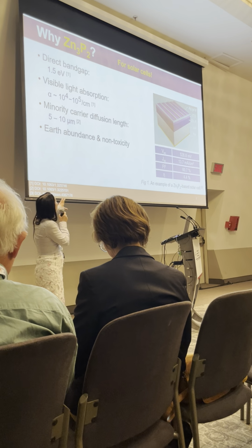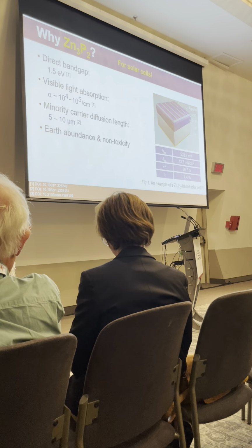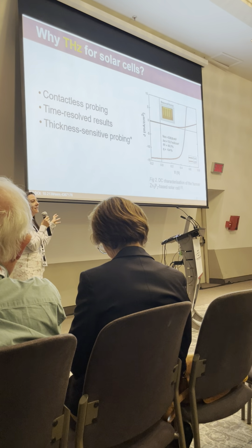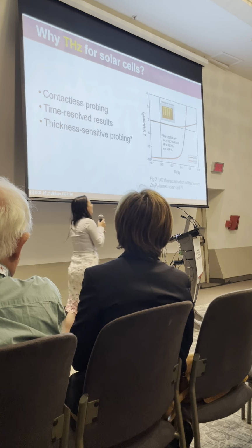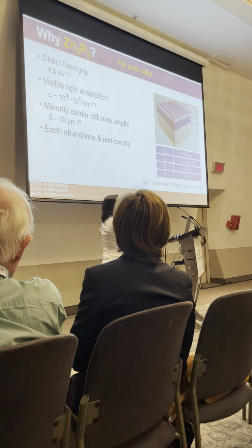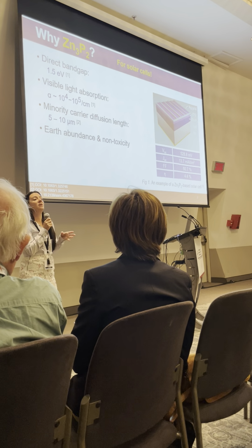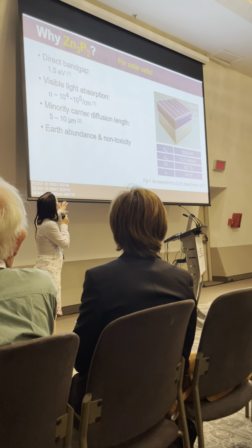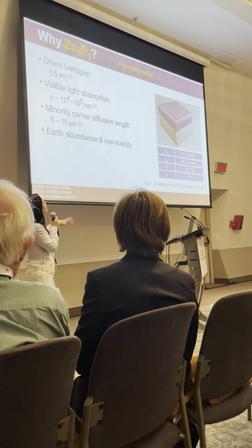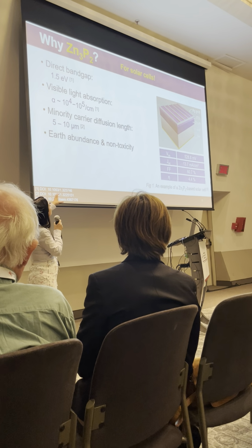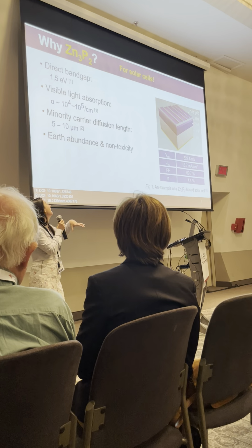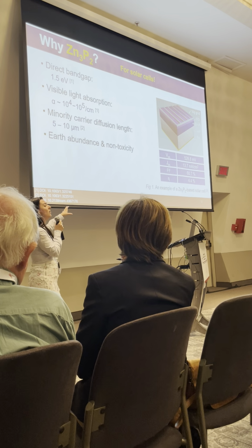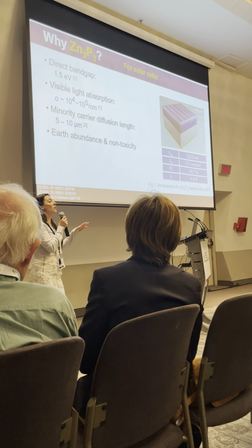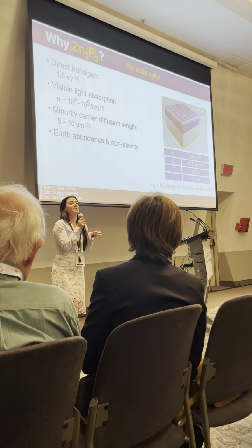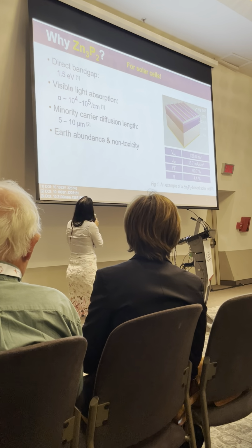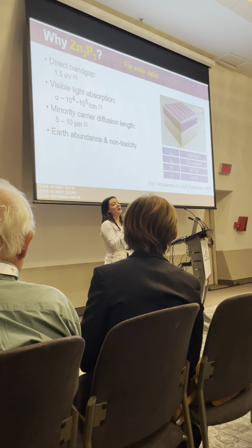Now, zinc phosphide is great because it's got a direct band gap at 1.5 electron volts. And that means that in the Shockley-Queisser limit, it's close to the optimal bandgap energy for solar cell operation. So it's a really good candidate for that, but its light absorption is also pretty good. It's got absorption coefficients on the order of 10 to the 4, 10 to the 5 per centimetre, and it's got quite long diffusion lengths. It's also not made out of any horrible lead things, sorry perovskite community, and it's earth abundant and non-toxic.